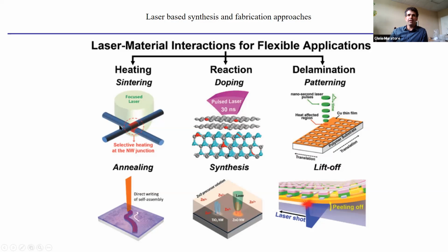So an example is if you have these 2 nanowires that are not making a good connection with each other because there's a bunch of junk on the surface, well, you could anneal them and have them make great contact. But maybe they're on a polymer and the annealing temperature is going to exceed the decomposition temperature of the polymer. So if you use a laser where these materials absorb the laser preferentially over the surrounding polymer substrate, you're going to have heating where you want it at the interface and not in the polymer. Maybe the laser passes right through the polymer and doesn't heat it up at all.